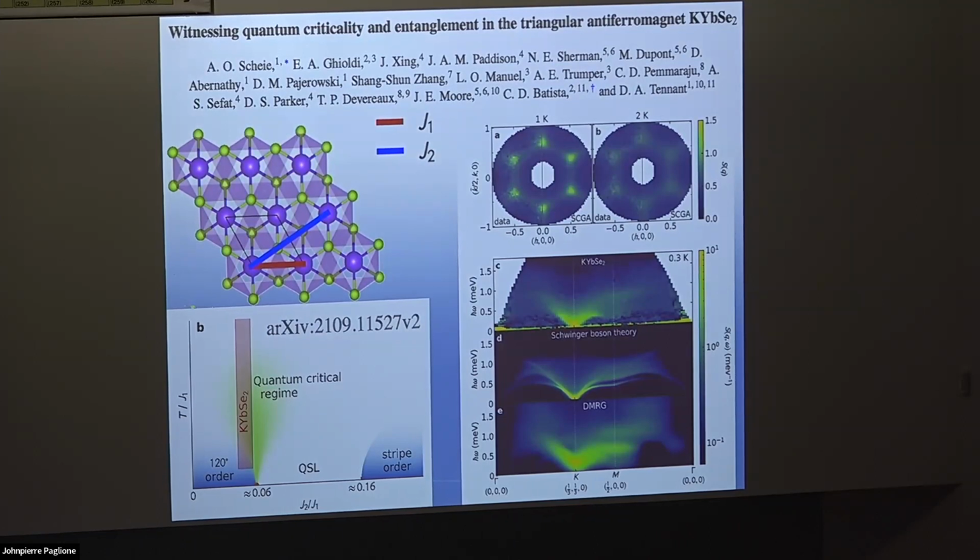And of course, initially when you look at this structure, you would say, well, this is kind of away from the magnetic side, so maybe it's not so important. But then you begin to think about why it is that I'm allowed to say that there's no Dzyaloshinskii-Moriya interaction. That has to do with the presence of inversion centers and mirror planes, etc., on the bond. And then you'd say, well, I'm looking at my best image of the structure, and it looks as if I do have some high symmetries on the bond. And so there's a tendency to say, well, then maybe I can still use those things, but in fact you cannot. Once you have anti-site disorder, all of these normal symmetry arguments just fall away completely. And now all of these interactions basically will come out of the woodwork.